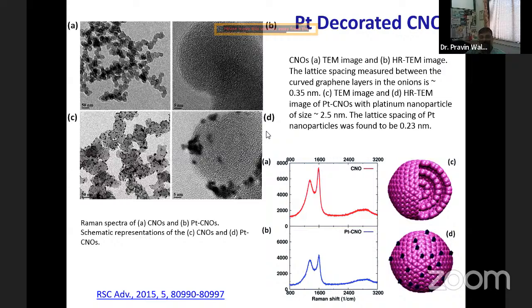Okay, let's look at one good example of the decoration of platinum on CNO. This CNO name has been given to this carbon material. Here you see this image. In this image, what you can see is a carbon nanoparticle of around 50 nanometers, right? And you can clearly see these small lines here. What do those small lines indicate? They indicate that there are graphitic layers, right? A number of graphitic layers assembled together, just like an onion. An onion has various petals around it, right? So each line here we consider as one petal. Various petals come together and form a ball-like structure, and that is known as an onion-like structure.